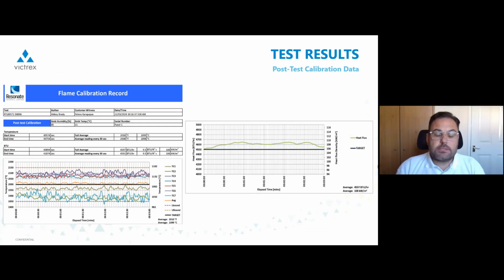Next slide. Yes, as I mentioned on the early slides, we start with the calibration, we do the test, and then we finish with the calibration. So this is what we call the post-test calibration data. Again, on the left is the data from the 9 Type K thermocouples, making sure that everything again falls within the upper and the lower limit, but also the average is actually where it's supposed to be. And then on the right is the heat flux. The black line is the minimum requirement. The green line is actually what we achieved during the test.